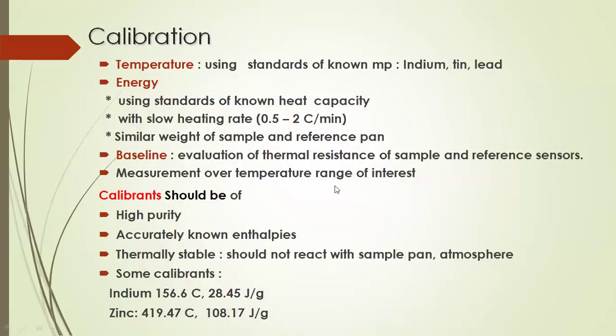Again, as I told you, for any thermal analytical equipment, calibration is very, very important. What are you measuring here? You are measuring temperature and heat change, energy change. So your temperature should be calibrated and your energy should be calibrated. Your supplier will give you standard known materials, which are pure metals, for which the delta H of fusion and melting temperature, Tm, are known. Usually, indium and lead are given with the instrument; indium melts at around 160 and lead at around 330. So you can calibrate your equipment over a wide range of temperature.